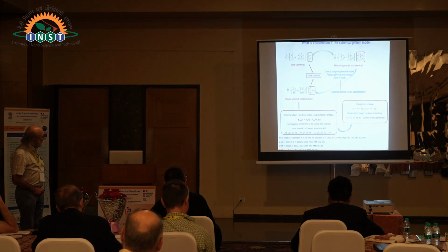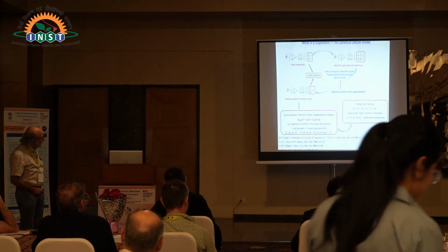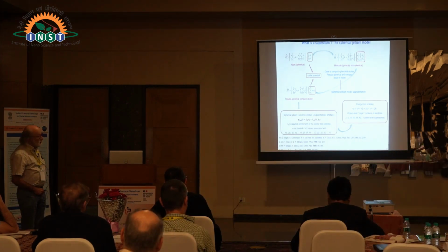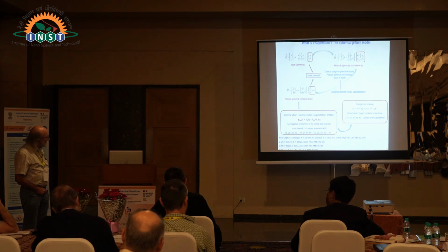And actually, we can express the solution of the Schrödinger equation based on this approximate Hamiltonian as a polyelectronic function which can be expressed on the basis of one electron functions that we will call superatomic orbitals, and which are also the product of a radial function and a spherical harmonics.